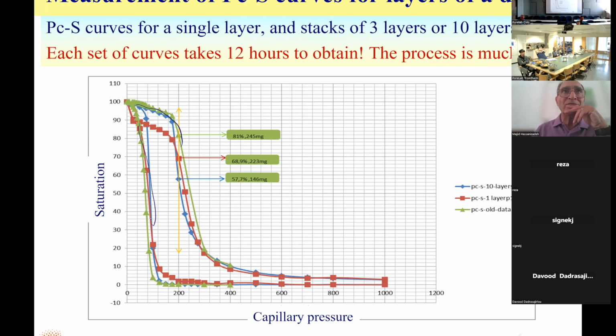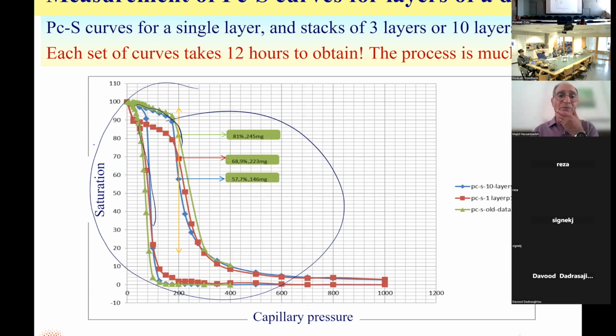So you get a curve that gives you a relationship between PC and saturation, but that relationship is developed over 12 hours. It has to be done very slowly. Whereas the process in a diaper, as you know, happens in 10 seconds or 30 seconds, going from dry to wet. So the process is much faster. And the question is, okay, if the process of wetting is much faster, can you really use these curves, or do you have to do something else?